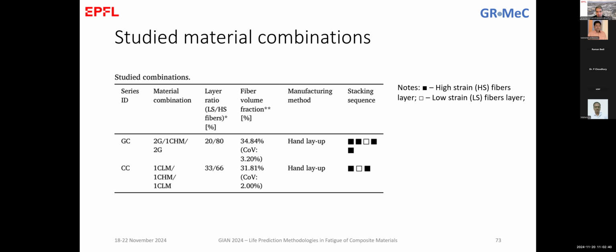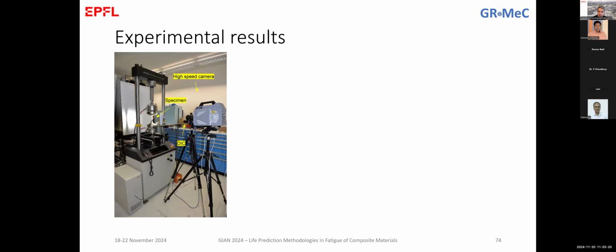So we mixed these two to investigate, as we said before, if there is any hybrid effect, actually to investigate the performance of this material, and if we could add or create ductility in the system. And this ductility, as you can imagine, we can artificially create. The material itself is not ductile, but by mixing these two components together, we can artificially create ductility, and that's why we call it pseudo-ductility. It's not a ductility of the material itself.